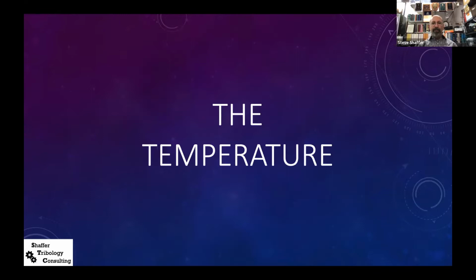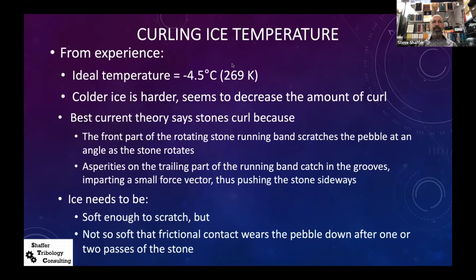And if we blow that up, we start looking at the temperature. Let's now find out where we are. When we're making ice in a curling club, we want to set it, and we find the ideal temperature is about -4.5 C. So below zero, obviously it's got to be freezing. But if we make it colder than that, it seems to decrease the amount of curl we get. And that's because certainly the best current theory, which I'll show you in a minute, says that the stones curl because the front part of the stone's running band is going to scratch the pebble at a mild angle as the stone rotates.